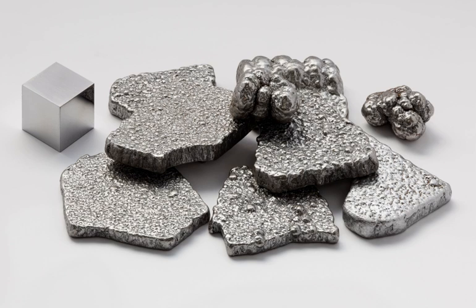These properties include high electrical and thermal conductivity, thermal shock resistance, damage tolerance, machinability, high elastic stiffness, and low thermal expansion coefficients. They can be polished to a metallic luster because of their excellent electrical conductivities. During mechanical testing, it has been found that polycrystalline Ti3SiC2 cylinders can be repeatedly compressed at room temperature, up to stresses of 1 GPa, and fully recover upon the removal of the load.